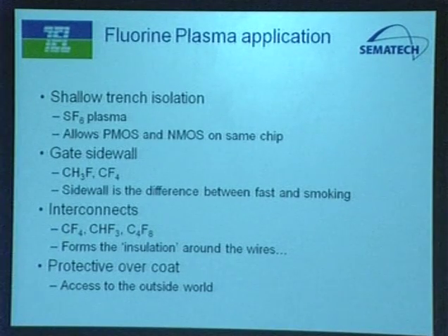Well, as it turns out, and I have personal experience with this, if you leave an aluminum film in the fluorine plasma for too long, you form aluminum fluoride, which is a dielectric, and you can't probe through it. You can't make electrical contact through it. It doesn't let that function happen.